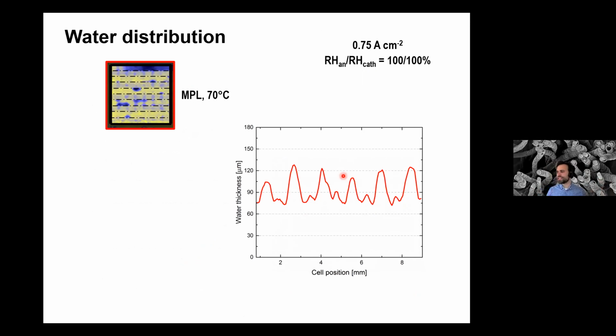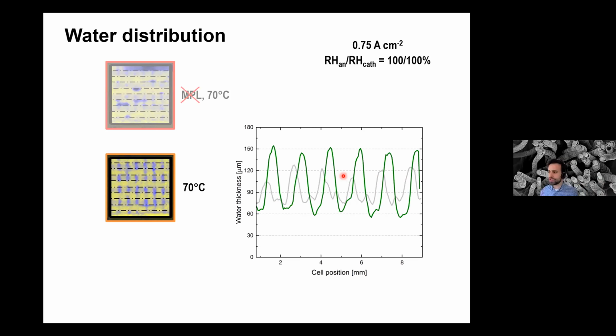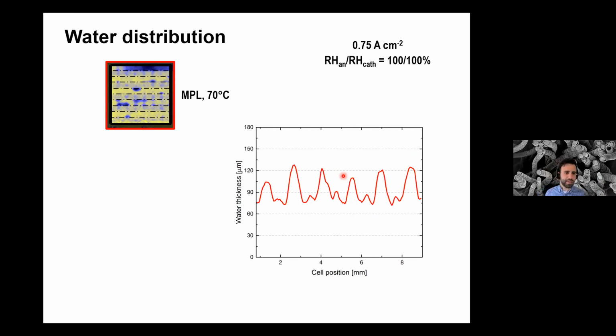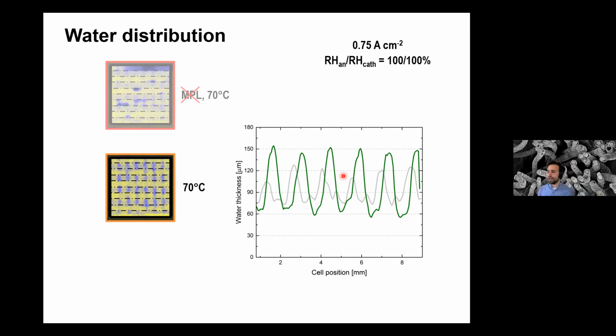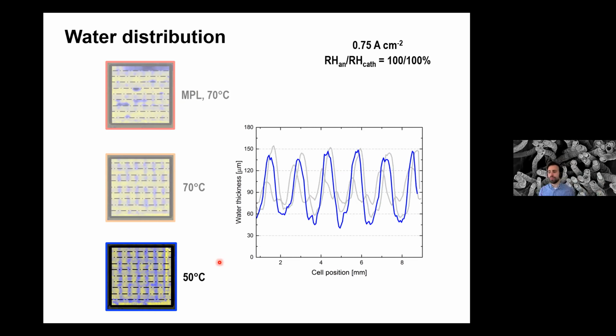Okay, and yeah, another exercise where you can use neutrons, and the reason why I put this here is because I realized that the work on CO2 electrolysis is going in this direction, which is beginning to use microporous layers, changing temperature as well. So here you can see the water distribution at 70 degrees and with a microporous layer. Here is when we remove the microporous layer, we can see that the water segregation gets even clearer. And when we go to lower temperature, you can see more condensation. And as a consequence, there is an even clearer segmentation between hydrophilic and hydrophobic.